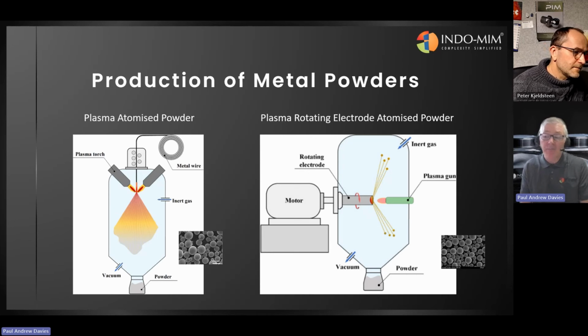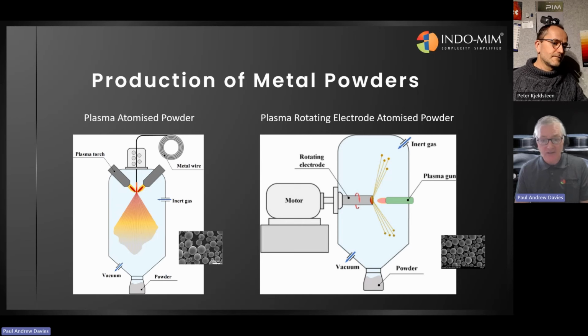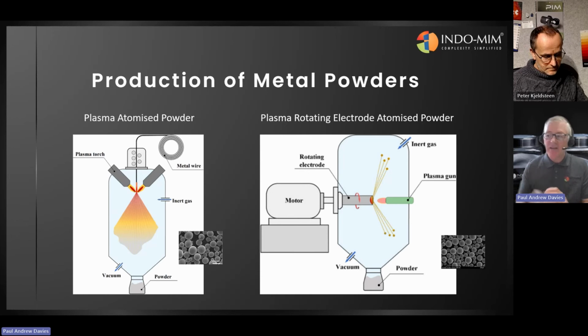And yeah, I remember seeing a plant making cobalt chrome alloys, and they were creating cobalt chrome powder, and they were quite coarse, 100, even 200 micron, and they were typically used to make sintered metal beads that were then sintered to a medical implant. Okay. And that provided a texture onto the implant where the bone could grow and almost key onto the surface of the implant. You could argue now that that's been superseded by 3D printing complex textures and surfaces on lattices onto the implants directly. So not necessarily needing so much PREP powder. But again, if you can get a bar, you can make coarse spherical powder in a batch process.